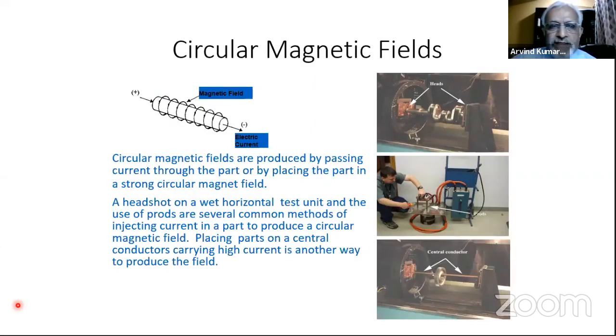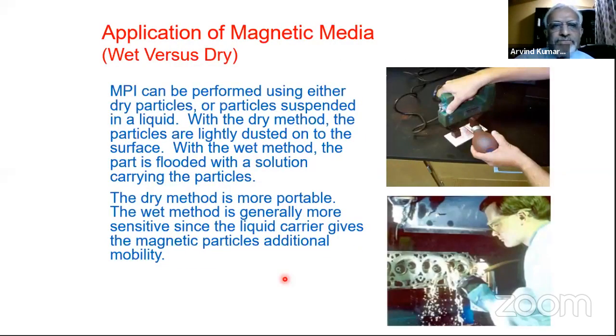Circular magnetization: when you are passing current through the conductor, you will develop a circular field. And this is again a head shot method where you are doing MPI. The various combinations are there, but you should know what you are using so that you are able to pick up all the defects. If you are introducing a longitudinal field, you have to make sure you rotate the part by 90 degrees and carry out the test again so that even the transverse defects you are able to pick up. Wet particle methods also, the same.